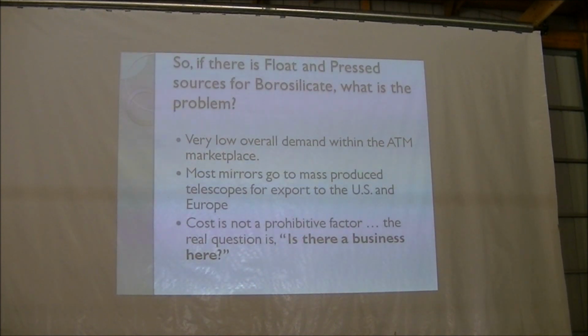Yes. There's a lot of trade names for different types of glass. Supremax, there's Schott Duran. There are a lot of glass ceramic varieties like Zerodur and Cervit. These are all high-end, high-performance glasses, and you pay for it. They tend to have very low, or even some have zero, or surprisingly negative coefficients of expansion, where they get colder and they actually expand and not contract. It's kind of weird how that works, but I guess like water when it freezes.